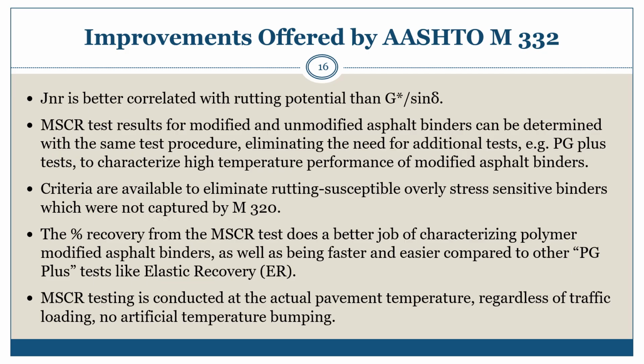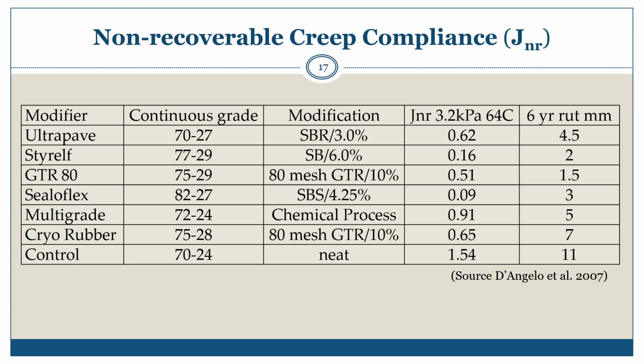Lastly, MSCR testing is conducted at the actual pavement temperature regardless of the traffic loading. No artificial temperature bumping. This table gives an example of the correlation of the non-recoverable creep compliance JNR to field rutting performance from a project in Mississippi. The data confirm the utility of JNR as an indicator of an asphalt binder's resistance to permanent deformation.